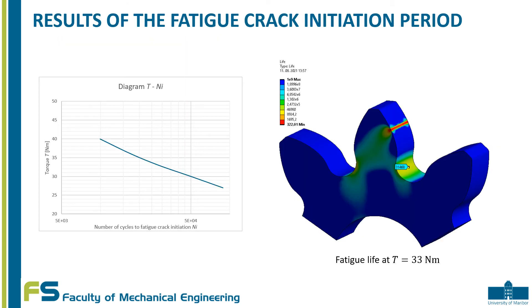The results of the fatigue-crack initiation period for the load case at torque 33 Nm are shown. At the point of maximum stress in the tooth root, the number of cycles to crack initiation was read. The graph shows the degradation curve, where lower torque corresponds to a higher number of cycles to fatigue-crack initiation.